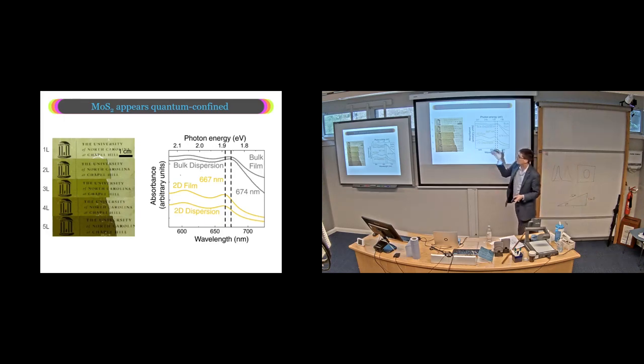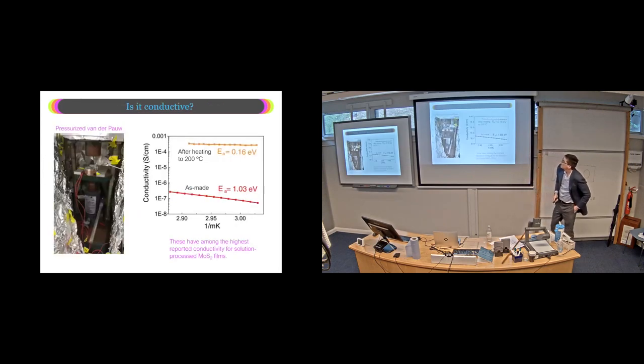If they're quantum confined, these films are probably not electrically conductive or terribly conductive. The flakes have to be somehow separated from each other. So they shouldn't be too conductive. To test that, to see if it's conductive, we built up this fairly complicated van der Pauw instrument. And tested as made films here. And so we found conductivities of about 10 to the minus 6 Siemens per centimeter. Which are already on the more conductive side for solution processed MoS2. So that was not expected. We thought these should not be conductive, but they were. And they also kind of appear to be quantum confined. So we wanted to go back and say, is this really quantum confined? We need to test this a little bit more carefully.